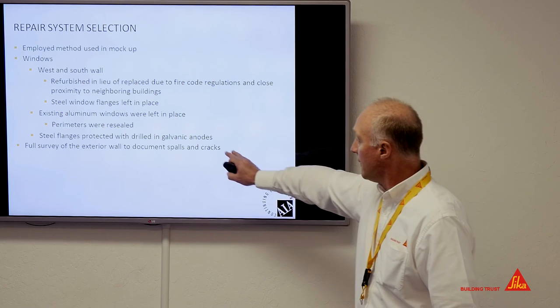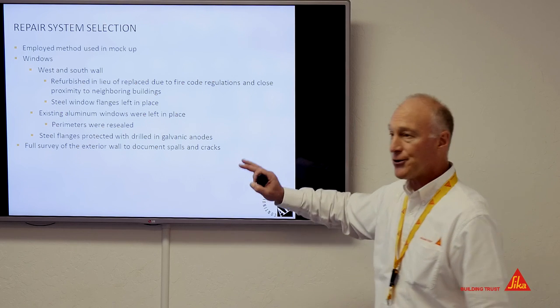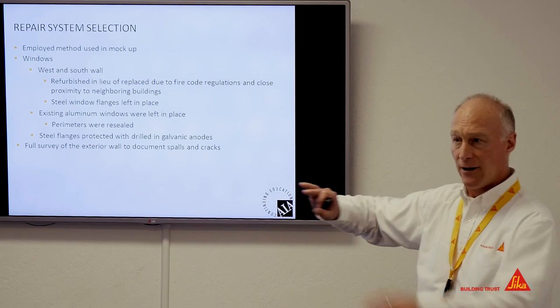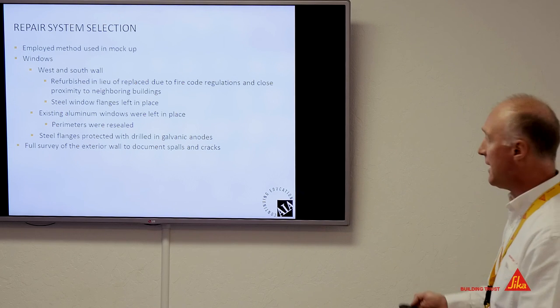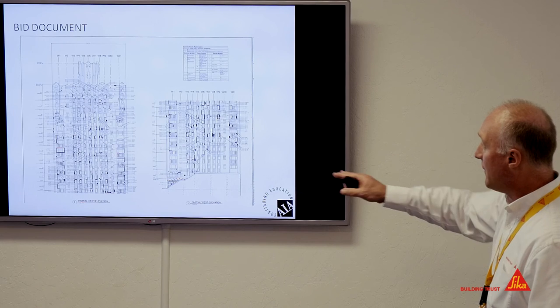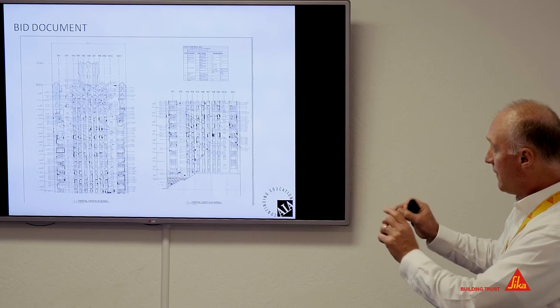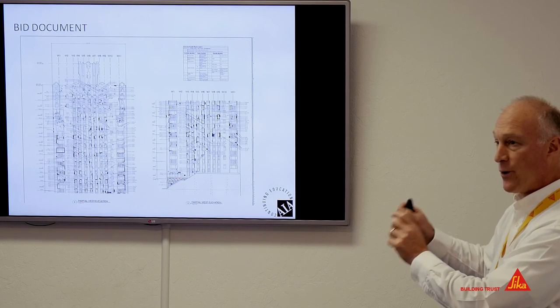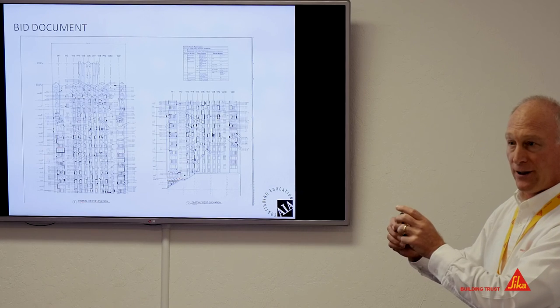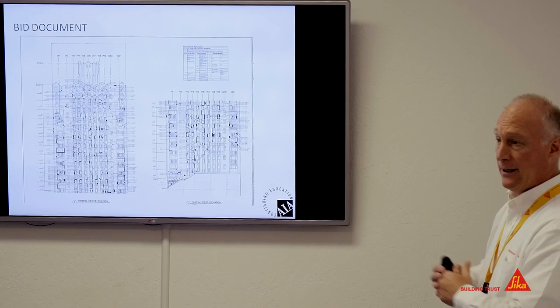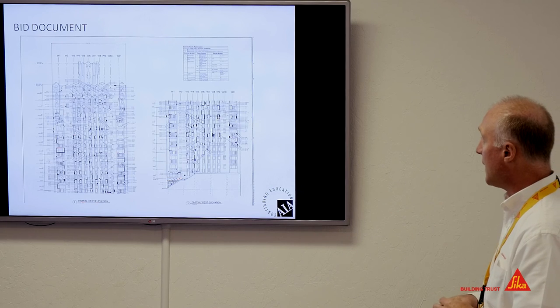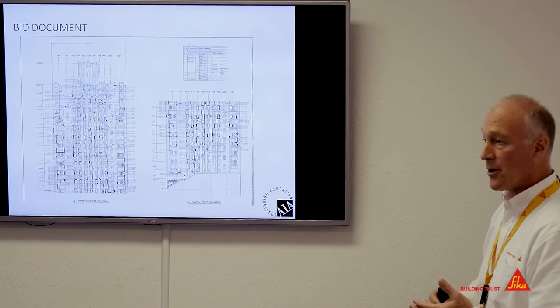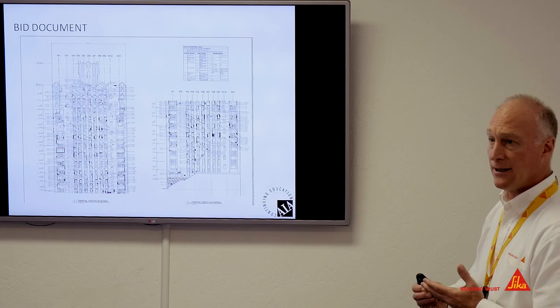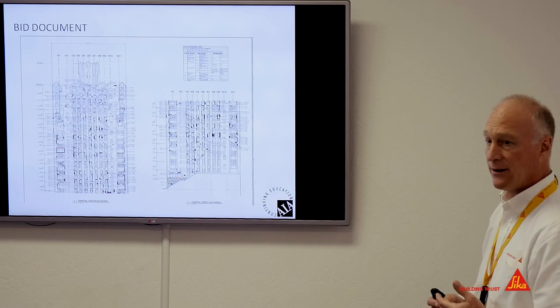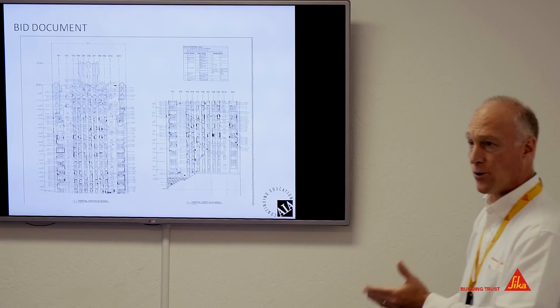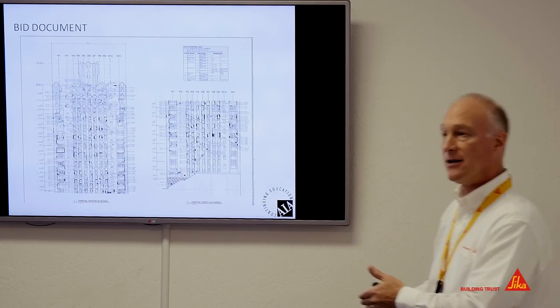And here, we don't see this on every job, but they did a full survey of the exterior building. 100%. Got their hands on 100% of the area. And when they bid the job, the consultant had a very good set of elevations of where they anticipated spalls that could then go out and be bid by, I believe in this case, it was five contractors who were part of both ICRI and SWRI. So two very well-respected, I haven't mentioned SWRI, but that's the Sealant Waterproofing Restoration Institute.